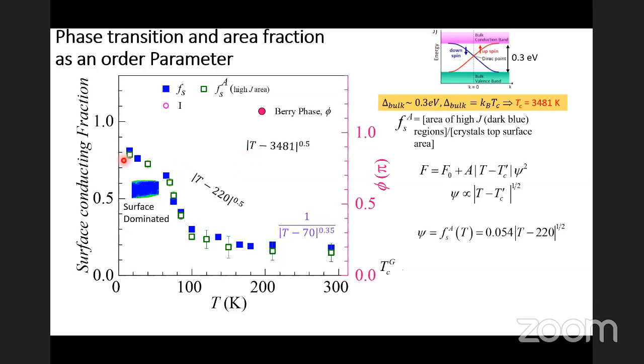Okay, and if you measure the 2D conducting region as a function of temperature, you see that this fractional area which contains the 2D surface state is decreasing monotonically as a function of temperature. But above 70 Kelvin, there is a rapid drop in this fraction, and this is the point where you break up these regions into smaller and smaller patches. As the bulk conductivity increases in the sample, the 2D surface conducting state breaks up into smaller and smaller patches. Okay, so now we wanted to actually look at this curve.